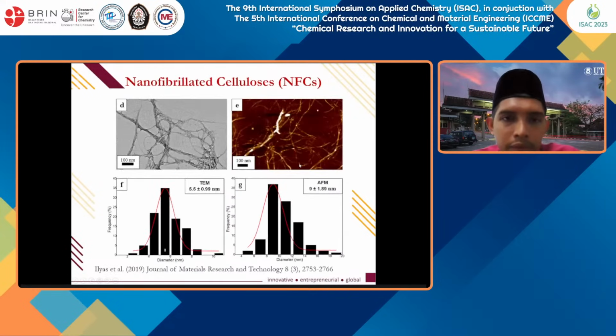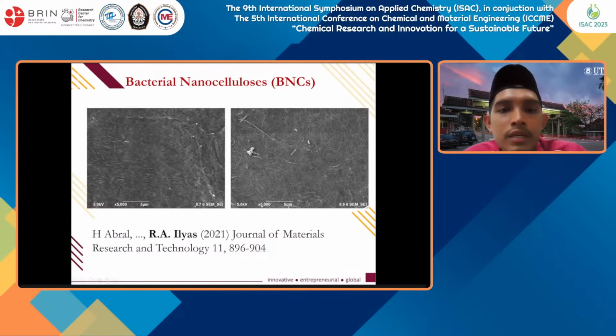This one is another type of nanocellulose, nanofibrillated cellulose, isolated from sugar palm fiber. We can see that it's like a thread or spaghetti, with the diameter of the nanocellulose at 5.5 nanometers and length of up to 1 micrometer.